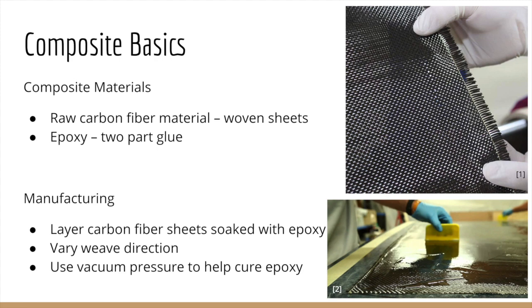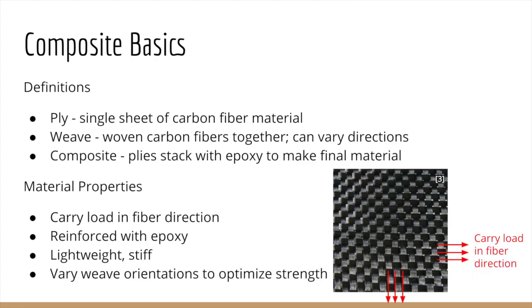On that car, you could see the outer surfaces, and those were all of our composite parts. But some composite basics. The composite material is raw carbon fiber, and we use a woven sheet, like the picture you can see on the right. The other part of the composite is the epoxy, which in our case is a two-part glue. This holds the carbon fiber sheets together. For manufacturing, we layer these sheets on top of each other, and often we vary the weave direction, and then we use vacuum pressure to help cure the epoxy that we mix in between these sheets.